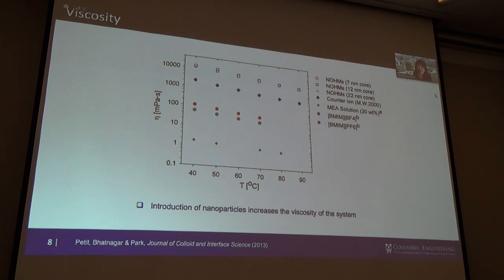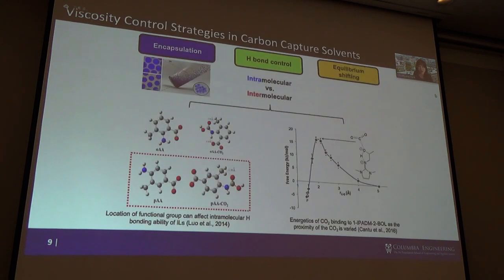But one of the things we went back to was, why do we really care about high viscosity? Well, there are a few things. It would be really hard to move these liquid solvents around between the CO2 capture reactor and the solvent regeneration reactor. But also, it would be very hard for us to create the interfaces between gas and liquid for CO2 capture. So that was about the time my colleagues at Lawrence Livermore National Lab came to me and said, well, there are a lot of these high viscosity CO2 capture liquid solvents, and they're very interesting, but they have these kinds of issues. So why can't we develop other technologies?